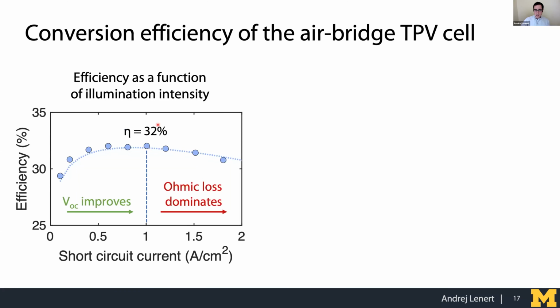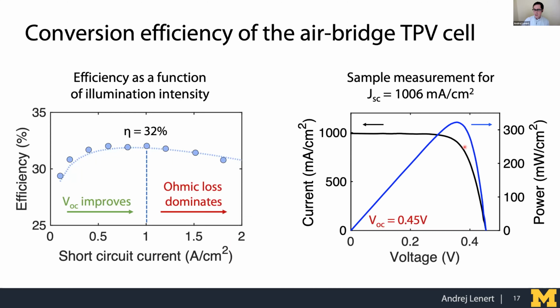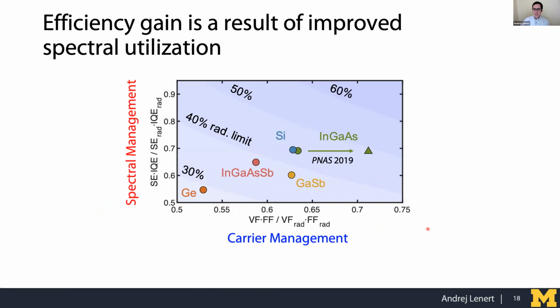But the peak efficiency, the peak absorption efficiency that we see in this device is around 32%. And the IV curves that correspond to that 32% are shown here with an open circuit voltage of around 0.45.